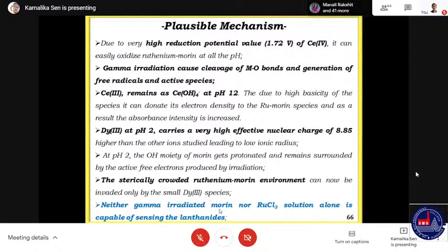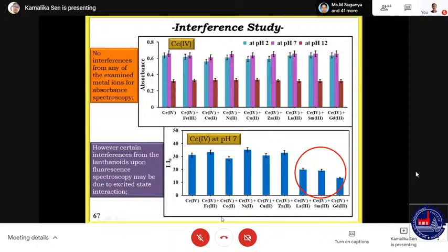So neither gamma irradiated morin only, which is the mother solution, nor ruthenium chloride solution alone is capable of sensing the lanthanides. Now we have studied the interference from other ions like iron, cobalt, nickel, copper, zinc, lanthanum, samarium. Absorbance shows no kind of interference. Results remain almost the same in presence of the interference. However, fluorescence shows some interference because it is a quenching type, and the studies are in the excited state. So the excited state interactions are present in presence of lanthanum, samarium, and gadolinium.